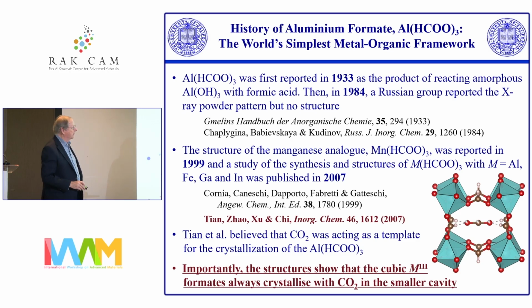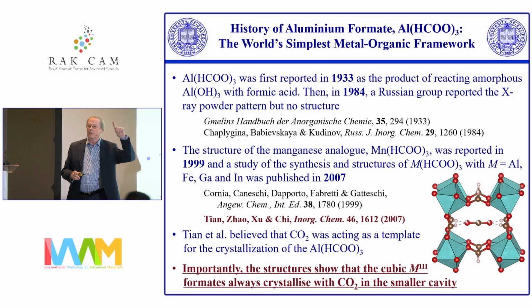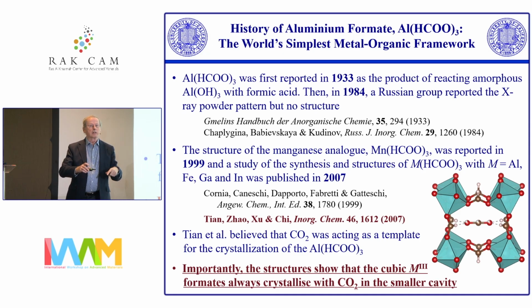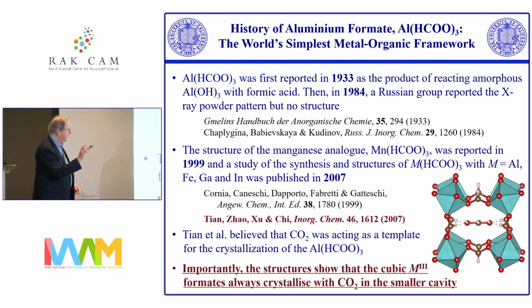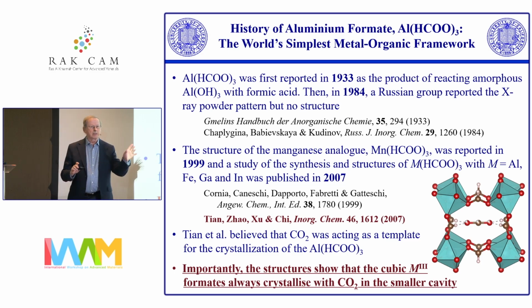And when we were doing the review, it struck me that if it's so specific for CO2 in the cavity, can we do two things? Can we get the CO2 out without collapsing the structure? And if we do that, can we get the CO2 back in? Does it become a good sorbent for CO2? And so the Chinese group had tried to do that, so they did see the potential of it, and they tried to do it with the iron compound. It turns out that the iron compound, you can't activate it and remove the CO2 because the iron 3+ oxidizes the framework when you do it, so it just collapses.